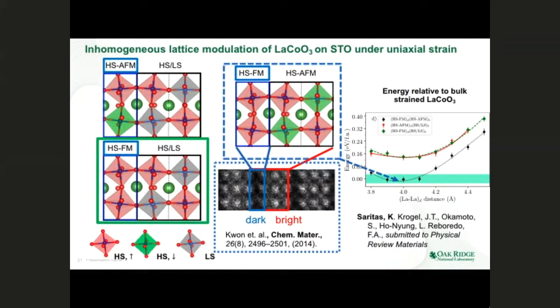And what we found in the diffusion Monte Carlo is that this structure, the high-spin ferromagnetic structure in the dark layer and the high-spin antiferromagnetic structure in the bright layer, which resembles the bulk structure, can be formed with a little energetic driving force compared to bulk strained lanthanum cobaltite, which has the same strain in this X direction. So we can see that ferromagnetism can occur in a system with a little lattice modulation. However, so far what we have found is that the experimental lattice modulations that are observed are nearly 4.5 angstroms, but we are seeing 4 angstroms, which is the lanthanum distance in the dark layer, which is basically the width of this blue rectangle.